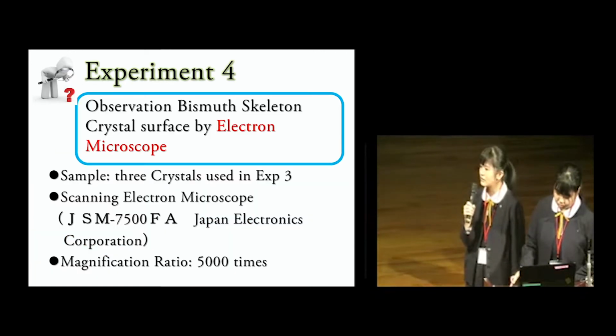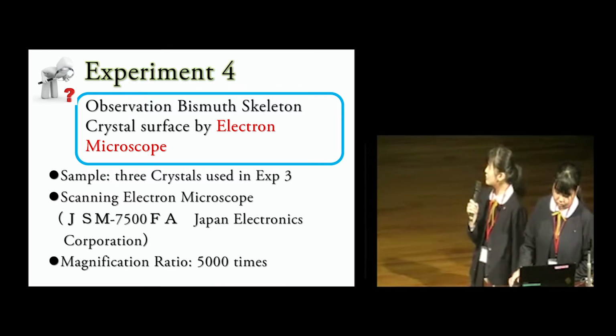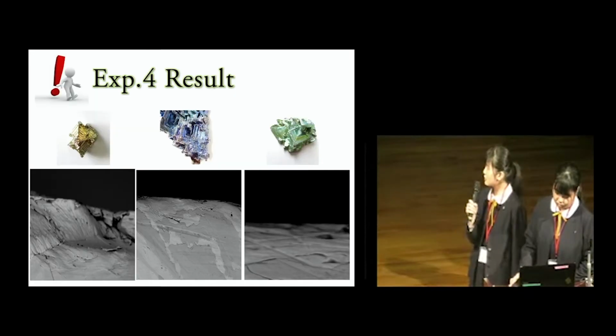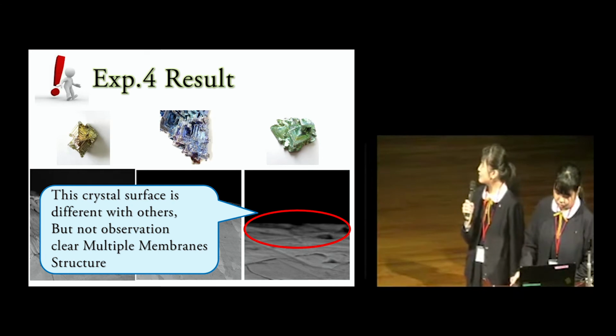In experiment 4, we observed the bismuth crystal surface with a scanning electron microscope. The samples were the 3 types of crystals used in experiment 3. Other experimental conditions were shown on this slide. The photos on this slide are micrographs of crystals of each color. The rightmost photo is a green crystal surface. Compared to other photos, we could confirm a layer-like crystal film on the green crystal surface. However, we couldn't confirm an obvious crystal film.